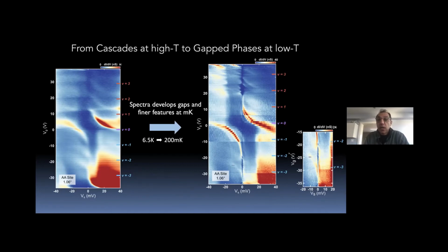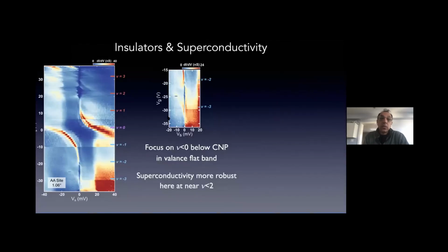I'm not going to say a whole lot about them, but let me flash a few results. So for example, this is the charge neutrality point. This is nu = -2. This is when you have 2 electrons filling the lower flat band, or you have hole doping, depending on how you look at it. And what we do see is an insulating phase at nu = -2, just like our transport colleagues see. And we see that nu = 2 state, which is where my arrow is.